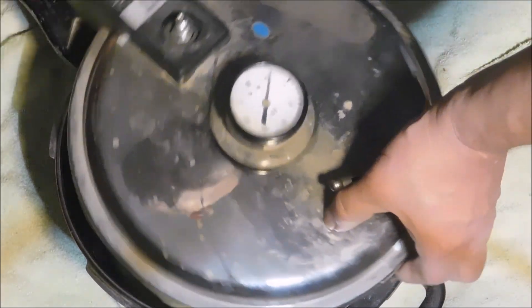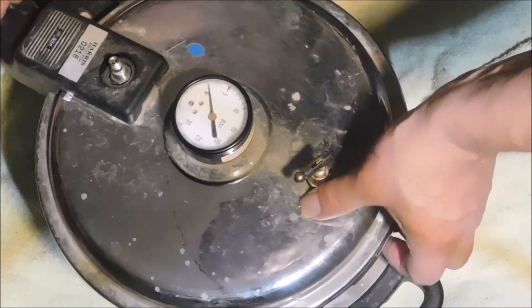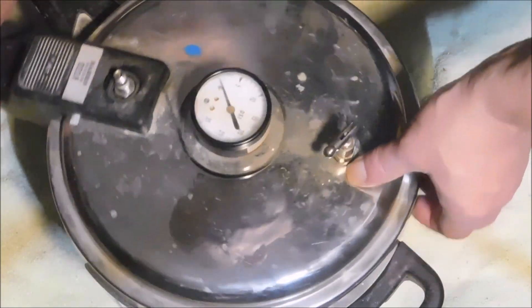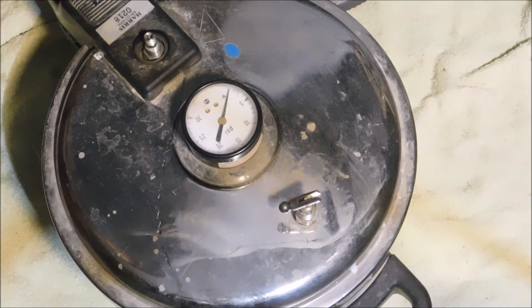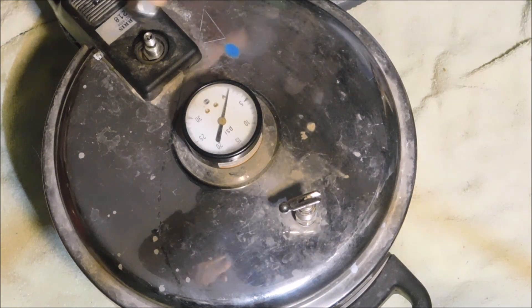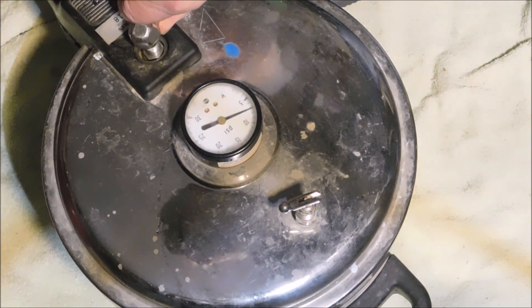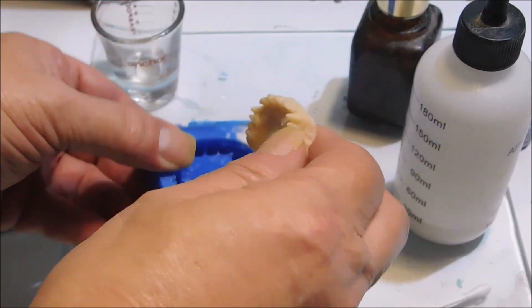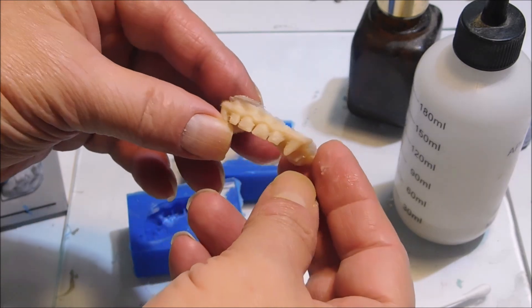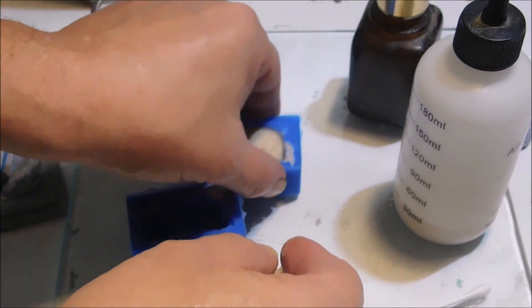Immediately you put it in a pressure pot with the water at a temperature of 100 degrees. This acrylic is called cold cure acrylic, also recognized as quick cure acrylic. Heat cure you have to really heat for like two hours in a press and boil it for almost an hour.